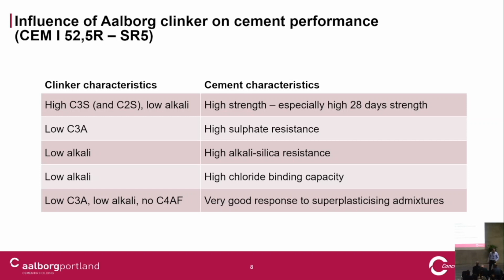But that's not the truth here, because with very low alkali content, that changes the balance between how much chloride is in the pore solution and how much is in the silicate phases. With low alkali, more chloride is bound by the silicate phases. So actually this cement also has good chloride binding capacity.